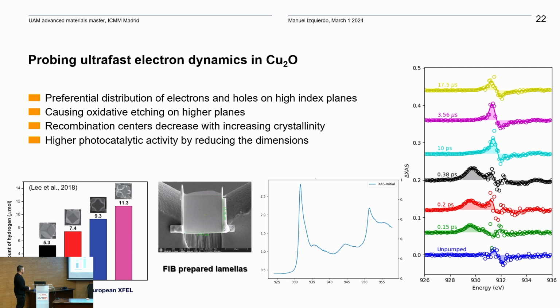So what we did in this case was we prepared 110, which is one of the low-index surfaces, because we just wanted to demonstrate that it was possible. You can see here the lamella preparation, you can see the absorption spectrum, and then what we did was a pump-probe experiment, and there we saw two things. On the one hand, we see here a prominent excitation at the pre-edge, and this is related to the production of the exciton due to the excitation with the laser.